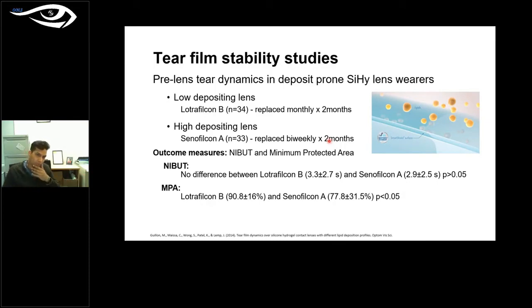Here we have Lotrafilcon B, which is a generation 1 silicone hydrogel lens, and then we have a generation 2 silicone hydrogel lens, which is supposedly bi-weekly. We had participants wearing both these types of contact lenses, and the lenses were worn for a duration of about 2 months.